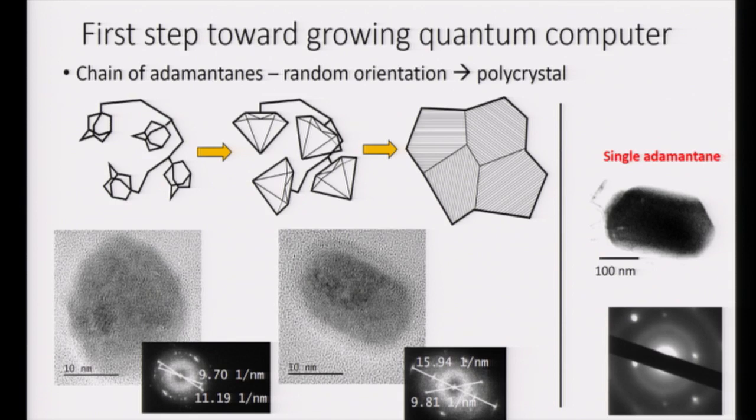It's polymer with some adamantane stuck on it. And if you grow a diamond around that, you predict you'll get a polycrystalline. And sure enough, when we grow with that seed molecule, we get polycrystalline. And the number of crystal domains is about equal to the length of the chain, whereas otherwise we get just a single crystal. So it looks like we're starting to get there, but there were no nitrogens on that, so we couldn't make any NVs. So hopefully the chemist will give us a nitrogen version quite soon.